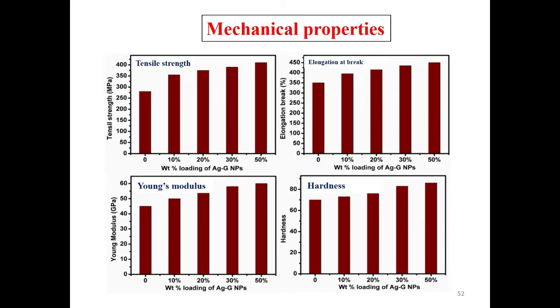This is the mechanical property: 50% loading shows high tensile strength, more than 350 megapascal. Elongation at break is more than 400 percent, and Young's modulus is between 50 to 60 gigapascal. Hardness is very high, and because of the hardness, this material can be used as a reinforcing material in polymers to improve their properties for the desired application.